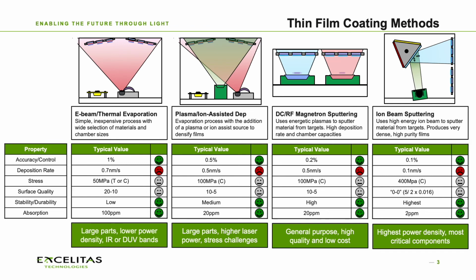But the ultimate in terms of film quality, if we're talking about wavelength ranges from the visible to the mid-infrared, is going to be ion beam sputtering. And that really has unmatched surface quality capability, unmatched absorption, and the density of the films, and thus the stability and durability of the films, is also really exceptional. So that's really our workhorse technology for this type of application. Most of the laser optics that we produce will be made using ion beam sputtering, and there are technologies for doing that up to 300, 400, maybe in some cases 500 or 600 millimeters in diameter. So it's really applicable to all but the largest optics in these systems.